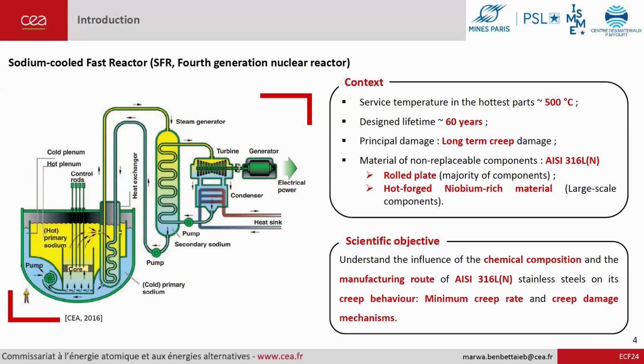So as part of the developments of the fourth generation nuclear reactors, specifically the sodium cooled fast reactor presented on the left here, the non-replaceable components are designed to operate in their hottest part at 500 degrees C up to 60 years. So the principal damage here is the long-term creep. The material used for these components is a 316LN stainless steel.